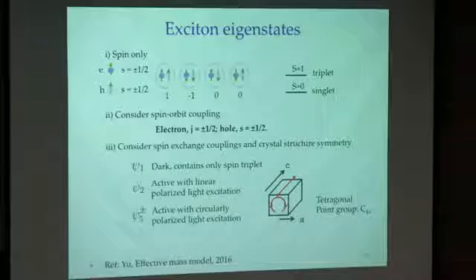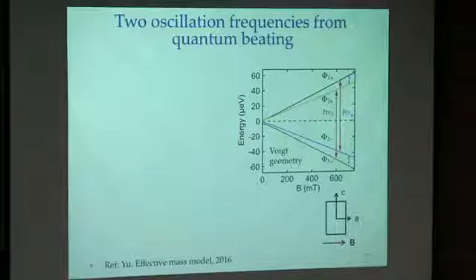But in magnetic fields, that's really what we need to figure out: what the eigenstates are. In magnetic field, those 4 states mix and split, and the energy levels of those 4 states depend on the strength of the magnetic field. With 4 states, if you choose one pair, you have 6 combinations of choosing 2 from 4 states. That means 6 possible energy differences. But with our optics measurement using the Faraday rotation, only 4 of those are optically active.